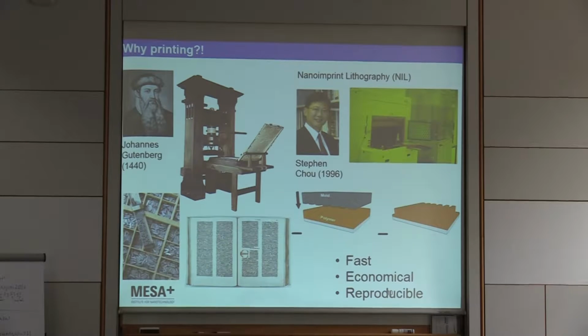The nice thing about this technique, and there are many things about it that are not so nice, but let me stick with the nice things, is that once you have your template and your features there, you can imprint it many times, no matter what kind of substrate. If the substrate is flat enough, it doesn't matter whether it is silicon or gallium arsenide or lithium niobate or graphene or whatever, you follow the steps of this imprint, and you can reproduce your features. That's much different from, for example, E-beam lithography, which would be a direct competitor, where you have to adjust dose and writing speed, depending very much on the substrate, whether it's conductive or insulating. So that is a very nice feature of NIL.